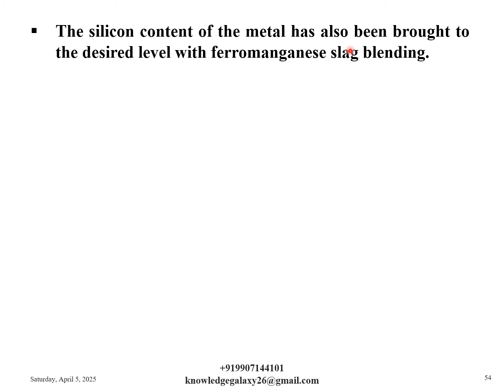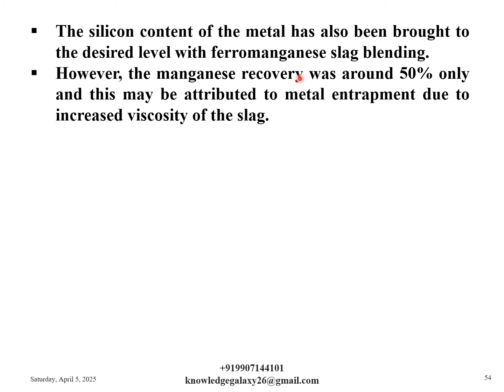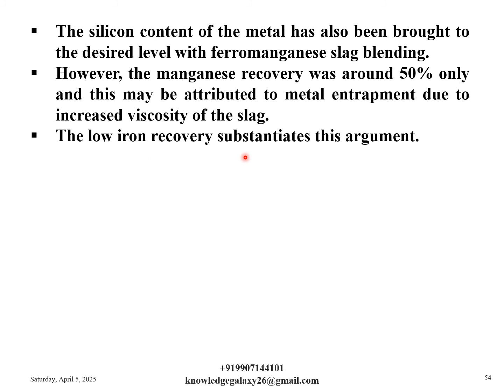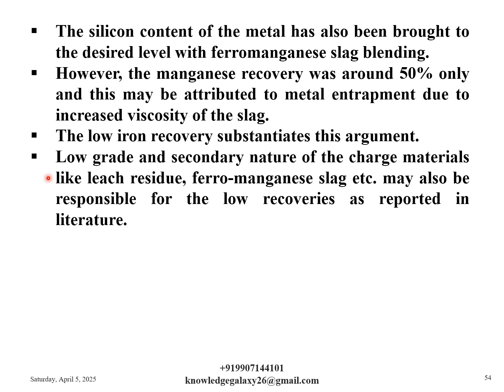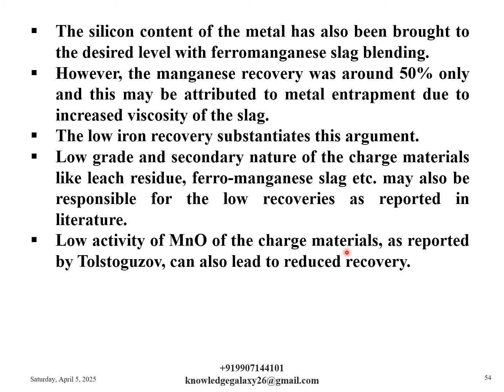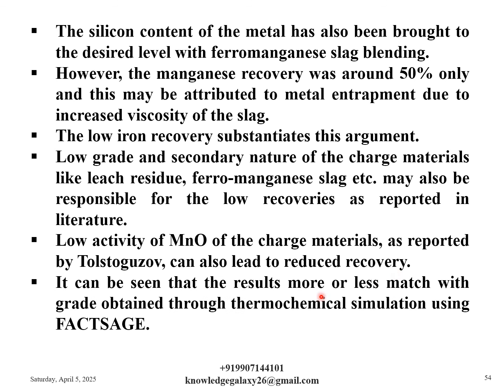The silicon content of the metal has also been brought to the desired level with ferromanganese slag blending. However, the manganese recovery was around 50% only, and this may be attributed to metal entrapment due to increased viscosity of the slag. The low iron recovery substantiates this argument. Low grade and secondary nature of the charged materials like leach residue, ferromanganese slag, etc. may also be responsible for the low recoveries as reported in the literature. Low activity of MnO of the charged materials, as reported by Tolstoguzov, can also lead to reduced recovery. It can be seen that the results more or less match with the grade obtained through thermochemical simulation using FactSage.